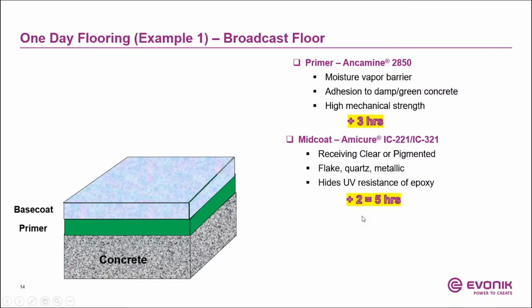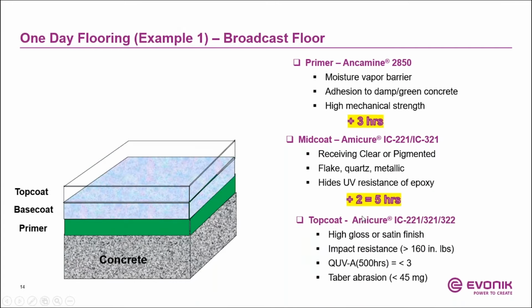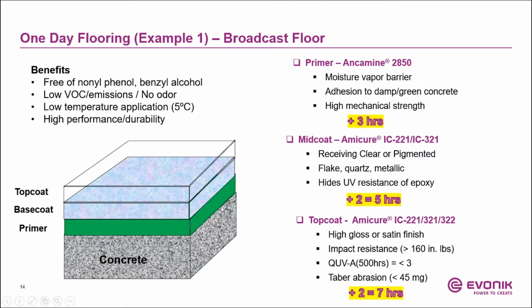And finally, 2 hours later, you put the top coat. So this is, again, we always recommend the polycarbamide technology, high gloss or satin finish, and get the improved impact, UV resistance, abrasion resistance by using the polycarbamide technology. So 7 hours later, you're done with the job.